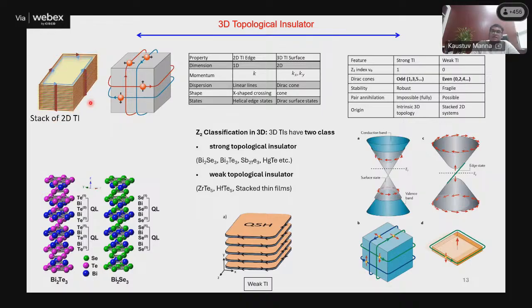It can give 3D, but the topological class will not be the same. The reason is that if you stack the 2D topological insulators, what happens? Not all the surfaces will have the surface states. As I said, in the 3D topological insulator, all the surfaces have the surface states. But if you stack, then the top and bottom, which are already part of that insulator, you cannot have any surface state.